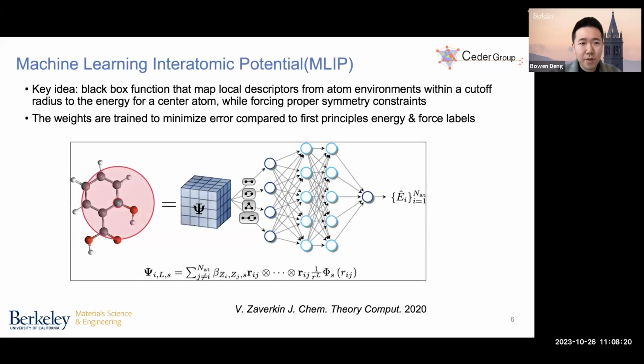So what lies behind these machine learning interatomic potentials? The idea is actually not that hard. The key idea is that we have a black box function that maps the local descriptors from atom environments within a cutoff radius to the energy of the center atom, while enforcing the proper symmetry constraints. And the weights of these black box functions are trained to minimize the error compared to first principle energy and force labels.